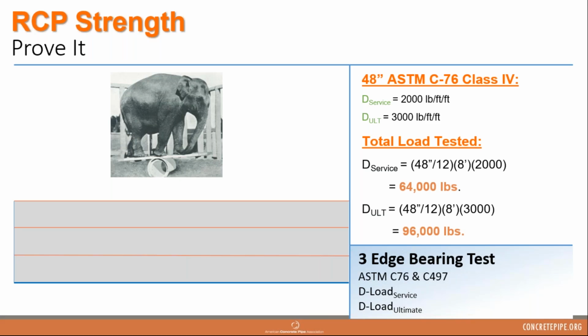So that pipe has to withstand 64,000 pounds on the D-load test, the three-edge bearing test that Felix mentioned earlier, before it reaches our service limit of a 0.01-inch crack. The same thing is true math-wise with the ultimate test: the ultimate loading works out to 96,000 pounds. So those are some big numbers.